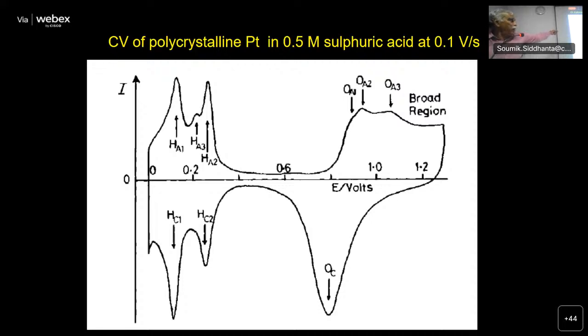This can be confirmed in a very beautiful manner. When you go to minus 0.1 or minus 0.2, hold it for 2-3 minutes. So what happens? Hydrogen is continuously evolving, by different mechanisms, Tafel, Heyrovsky, etc. But hydrogen continuously evolving means it gets saturated. So you will see this peak area will increase. Holding the potential at various points, you can control the amount of hydrogen adsorbed. So HA1, HA2, HA3, etc., different sites. And you can also calculate the coverage.